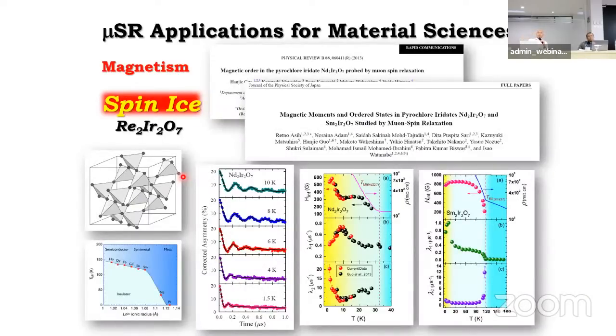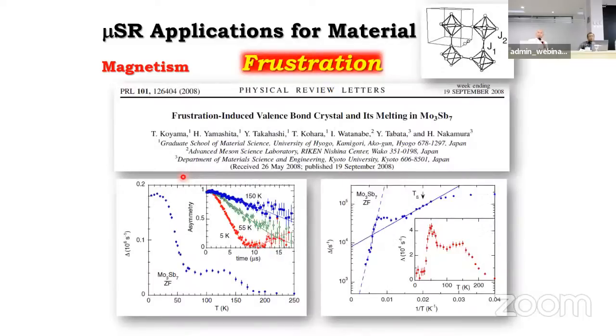And this one is also how to study the change in magnetic ordered state. The spin ice. I'm still working on this. My student is still working on this spin ice and also the pyrochlore system to investigate these days the monopole state. So the monopole state is not very fashionable, but not so easy to pick up. So then we are now trying to reach such kind of monopole state by using muSR and neutron. So then from last year, I started to use the neutron at JRR3 based on this pyrochlore system. So my student is trying to synthesize single crystals of some systems. So then once we get them, maybe we can enjoy muon and neutron as well to reach the monopole state.